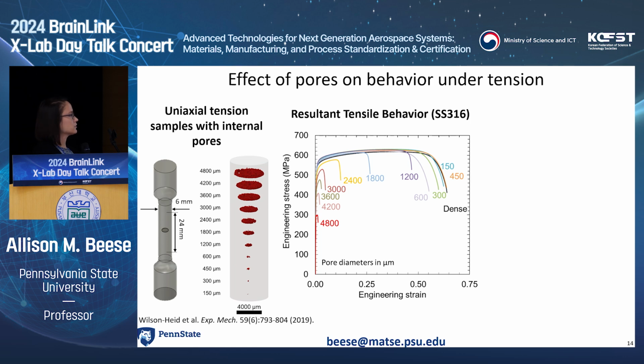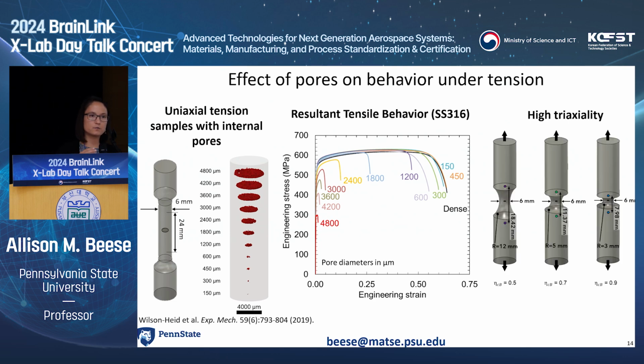So we would have our stress strain curve for a dense material in black, and then the different colors and numbers represent increasing pore size: our ductility drops off, and then eventually our strength drops off. And then we said, well, that's for uniaxial tension, but what if we now have something that's really going to accelerate the failure of those pores and rip open those defects? So these are notch tension specimens, which will reduce the ductility further.